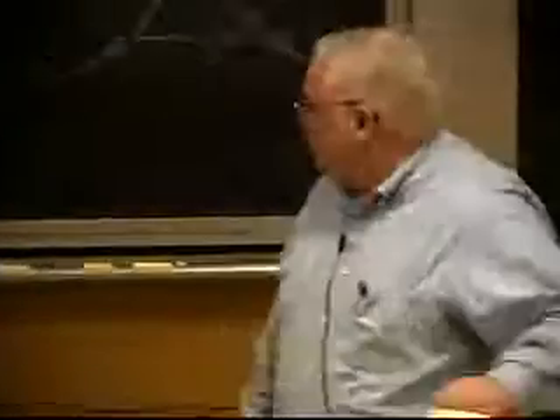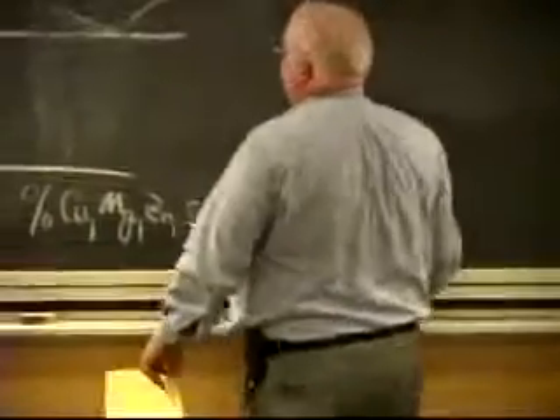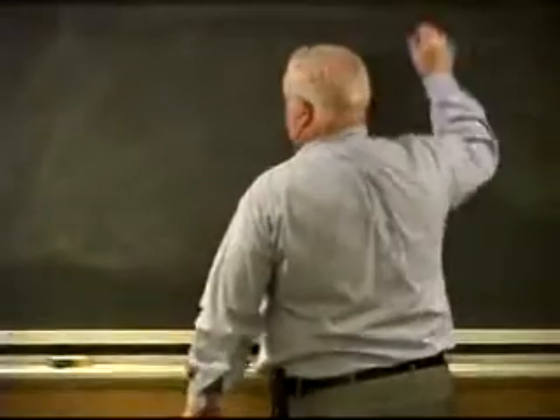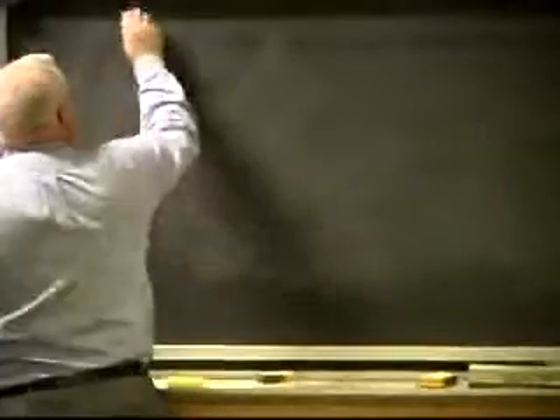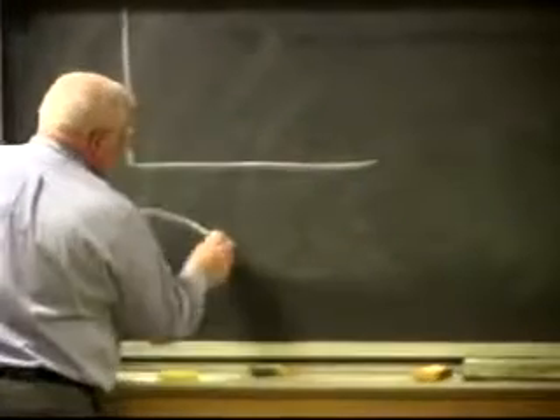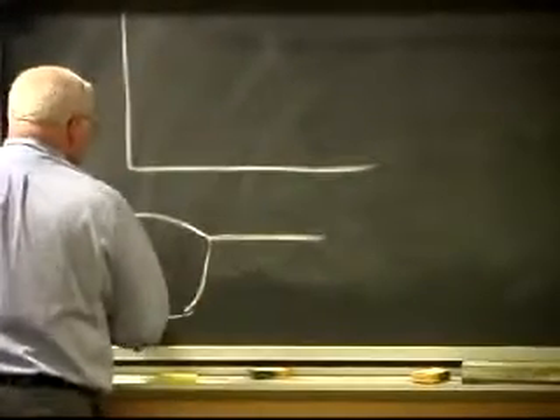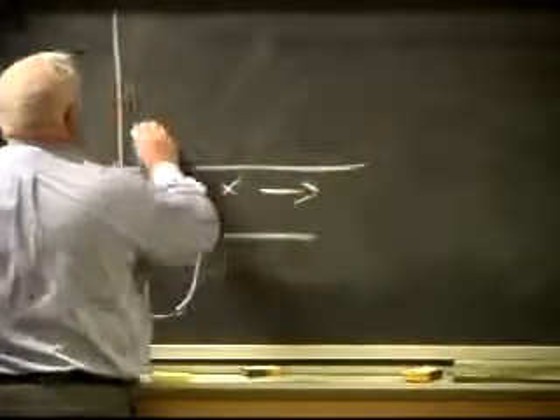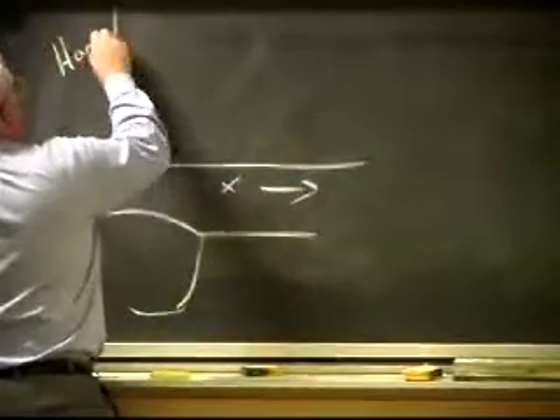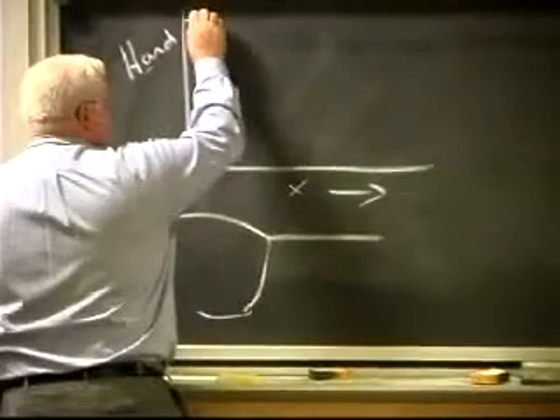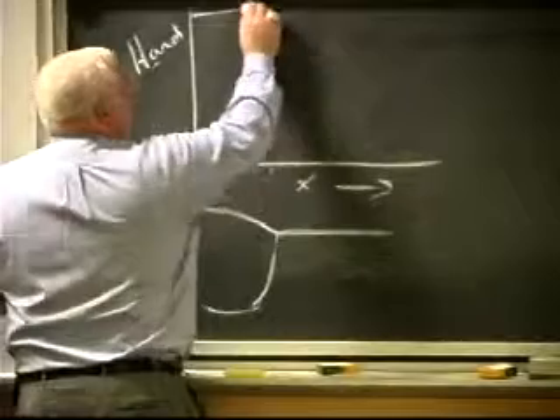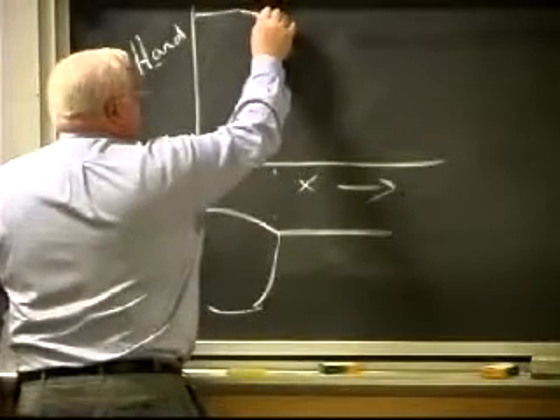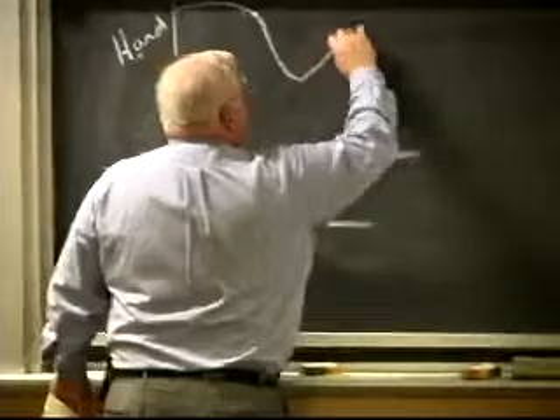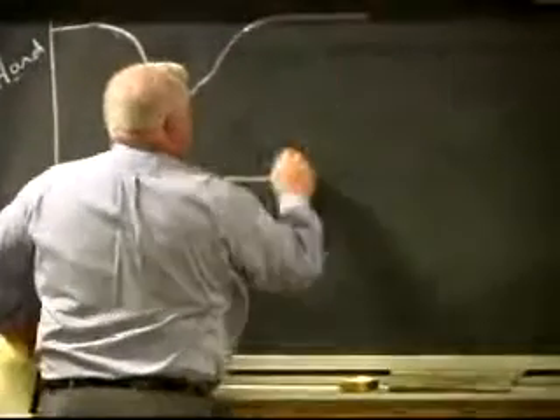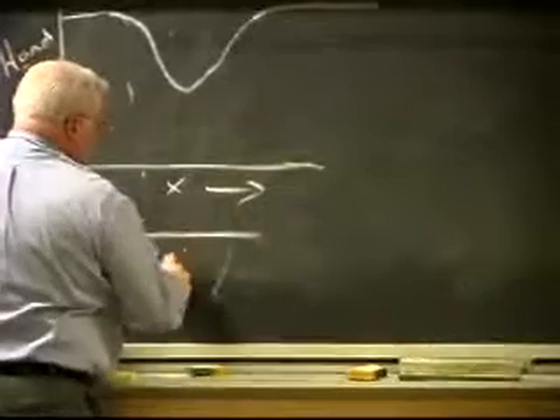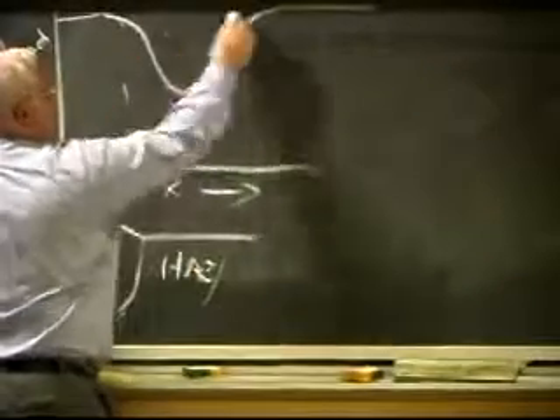And if you were to look at the hardness across the weld metal, so if this is my weld in the aluminum, and this is distance, I'm going to plot distance across here, and you were to just do an indentation hardness, you'll have high hardness in the weld metal because you're essentially going to make a highly alloyed casting, and then it will drop off fairly precipitously, and then it will come back up to the full base metal hardness. So I have this weak heat affected zone. I have this significant weakness in the heat affected zone.